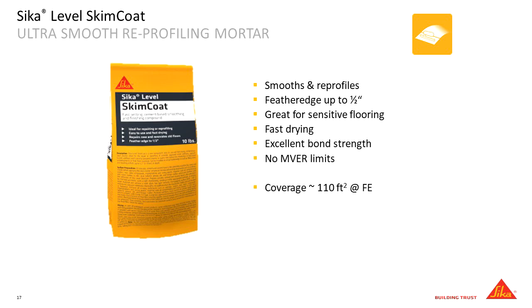Well, what inevitably happens is if you have a slab that is emitting 95% relative humidity and you think you're covered with your adhesive, you may be, but you may not be covered with your patch. So what happens is that constant drive of moisture up and down through that patch. It's going to travel up, hit that adhesive that won't allow it to go anywhere, and then it's going to sort of bounce around and sort of stick in that patch. Over time, that causes these patches, these older generation patches, to break down and soften, become almost like a Play-Doh type consistency. That's when you start seeing all these indentations in your vinyl flooring.